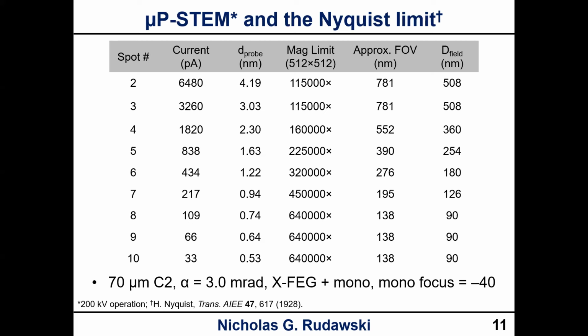So we can calculate the depth of field. Okay. So we can see here that the depth of field is corresponding to the field of view indicated, from which you can calculate a pixel size. So we can see here that our depth of field is getting less as we increase the magnification, which is exactly what we would expect. Okay. But we're at several tens of nanometers into the hundreds of nanometers, depending on what spot number we're at.